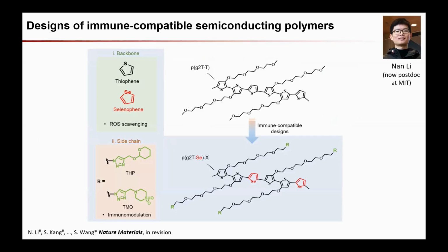Basically, the idea we came up with has two aspects. The first aspect is about the backbone of the semiconducting polymer, which is the most distinct feature of this so-called conjugated polymer. As I mentioned earlier, we do not want to sacrifice the charge transport. For conjugated polymer, the charge transport is mainly determined by the backbone structure, from having this pi conjugated unit. So the idea is to utilize a different kind of conjugated unit, a pi aromatic unit, to incorporate selenium, which is in the same group as a commonly used aromatic unit, sulfur, so that the conjugation can still be kept, but it could possibly benefit from the immune active property of the selenium. This is our first part of the idea.